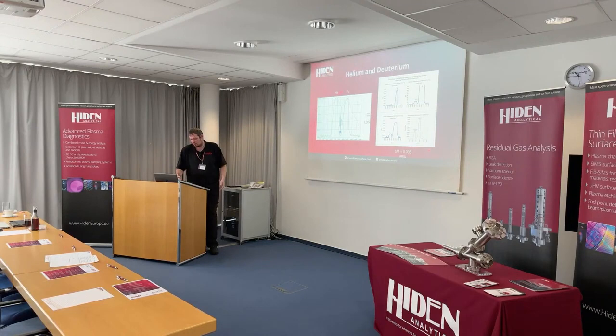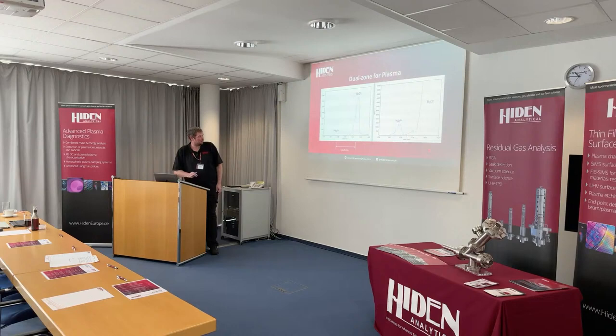0.005. As you go up in mass, it's not possible to do 0.005, but we can do this. This was again done on that chamber, just using the residual water in the chamber and the argon in the argon plasma. There we can separate 0.028 AMU. These will both be a nominal mass of around 18.